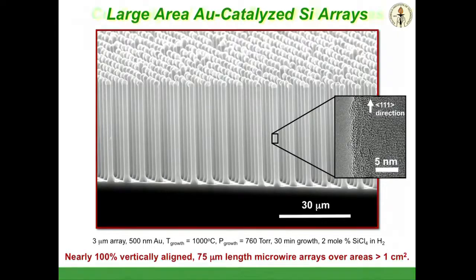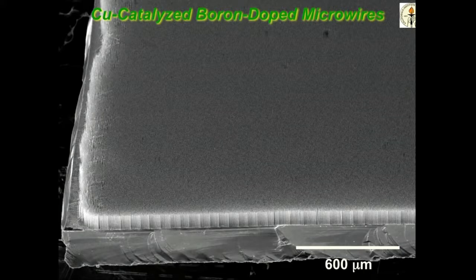Here's an example of a wafer grown from copper. Most people shudder when they think about copper and silicon because copper, it turns out, diffuses everywhere, which is why you never use it to make integrated circuit devices without extensive precautions and barrier layers. We actually love it because it's the ideal dopant in the sense that because it diffuses so quickly, it goes everywhere, which means it gets removed everywhere. And so we can oxidize the wires and then gather the copper out and then etch them off and there's no copper left. So we can use it as a cheap growth catalyst without degrading the minority carrier lifetime and actually recycle the copper in this way in a very cheap, fast process.